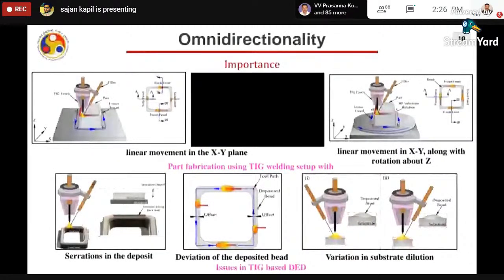What is the issue? You can see on the bottom part. Serrations may happen in the deposition. The parameters, the feeding angle, and the location of entering the wire into the molten pool, which are optimal for front feeding, may not be optimal for back feeding. Sometimes it has occurred that the wire itself makes a cut into the deposited path, and we get a cut like you can see here. This is called serration in the deposition. The solid wire, which is not melted, just makes a groove into the deposited bead. The second issue we have found is the deviation in the deposition bead.